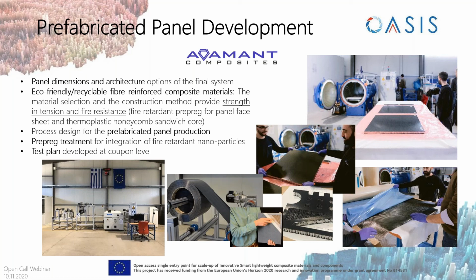Fire-retardant prepregs for the panel's face sheet have been selected. Inside the panel will be a thermoplastic honeycomb sandwich core. The panel will be covered with a layer of sound-absorbing mat on each side and can also be covered with a fabric to complete the process. The material selection and the construction method provide strength in tension and fire resistance. And because we need our product to be somewhat rigid, yet lightweight, using the thermoplastic honeycomb core is the perfect material choice.